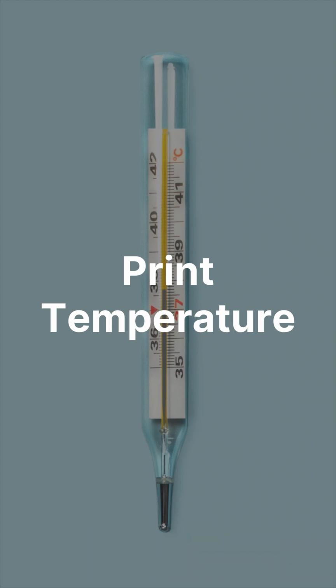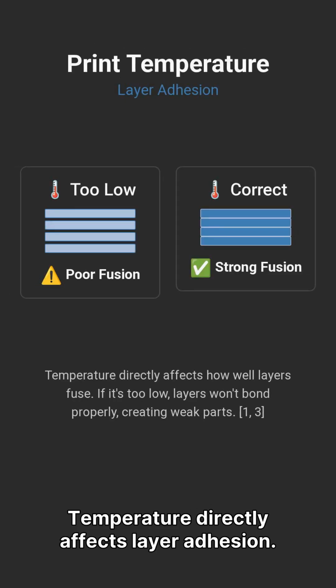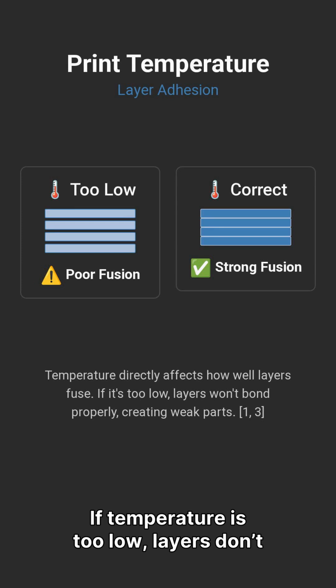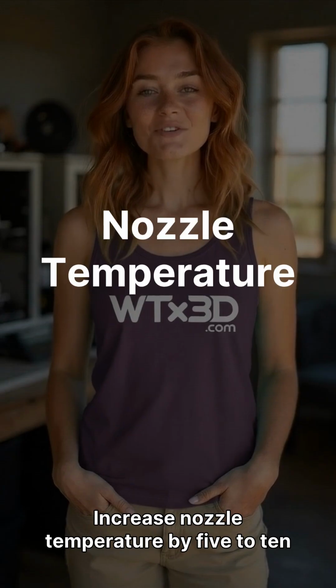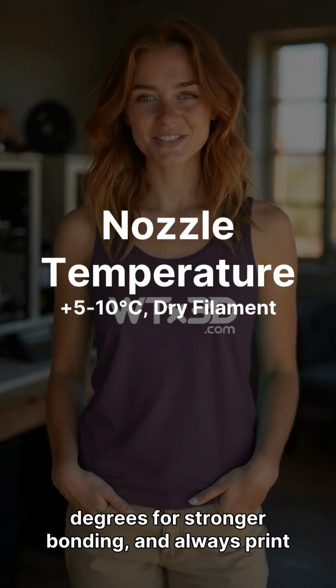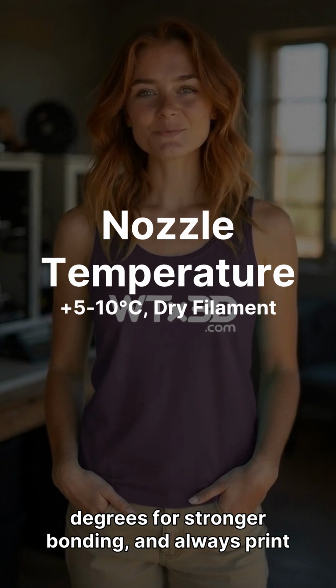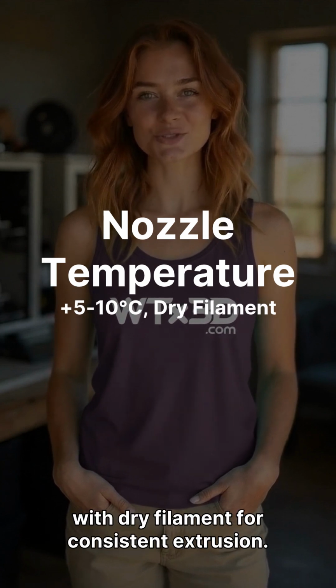Now print temperature. Temperature directly affects layer adhesion. If temperature is too low, layers don't fuse properly. Increase nozzle temperature by 5 to 10 degrees for stronger bonding, and always print with dry filament for consistent extrusion.